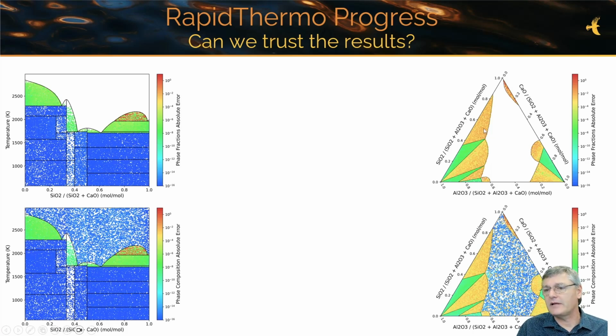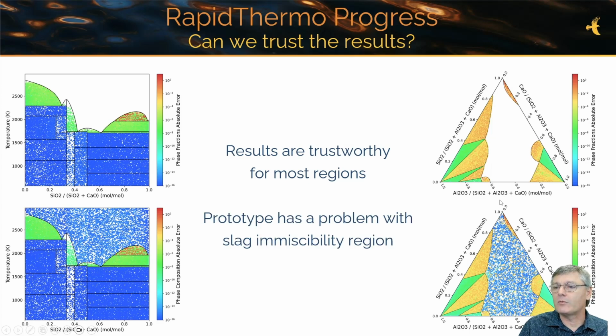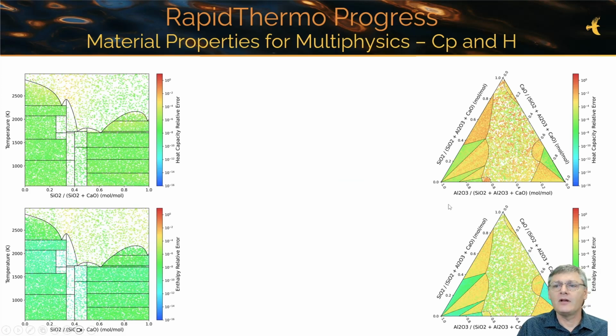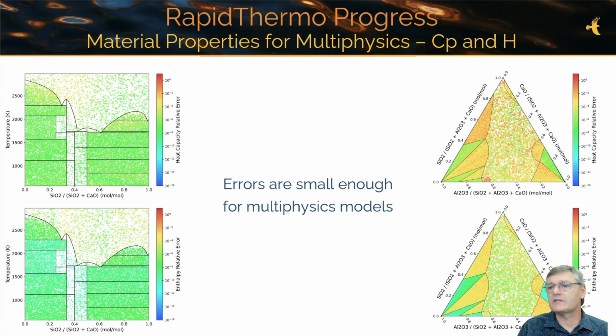Similarly, in the ternary diagram, we see errors between the accelerator and ChemApp calculations, which are quite acceptable when we consider using them in an open implementation. If we then look at properties like heat capacity and enthalpy, we can see here that the errors that we made in the binary system are in the order of 10 to the power of -8 or -7, slightly larger in the ternary system because of further interpolation that we need to do, but we do believe that these will be reduced in the next prototype as well.